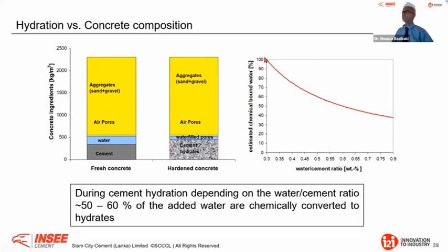Now, if you look, for example, at the right graphic here, you have the estimated chemically bound water, and you have here the water-cement ratio. Therefore, you see that if I want to chemically bind my water with all the cement hydrate, therefore fully hydrate my cement, I need approximately 0.3 to 0.35 water-cement ratio. In this case, I will almost not have any water-filled pores, therefore no more porosity, or a little bit of porosity. Therefore, I will have a very dense microstructure where most of the pores are gel pores because they have fully participated during hydration, where the water is chemically bound.